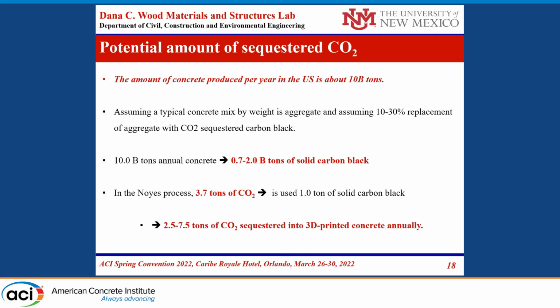The calculation is also simple about how much we can really store with this. I'm just making some calculations based on basic knowledge. There's about 10 billion tons of concrete produced in the United States every year. Assuming that a typical concrete mix by weight is about 70% aggregate, and that we can replace, with the numbers we are doing our testing on, between 10 to 30% of this aggregate with the CO2 sequestered carbon black, the 10 billion tons will include somewhere between 0.7 to 2 billion tons of the solid CO2 sequestered carbon black.